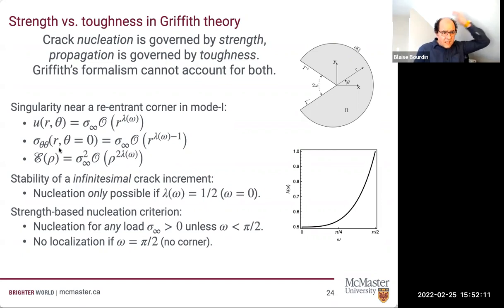If u is in r to the lambda, sigma is in r to the lambda minus 1, then the elastic energy density is the integral of sigma squared. So if you look at the elastic energy in a ball of radius rho centered around the crack tip, it is going to be in rho to the 2 lambda. Then you play the trade-off game: introduce a crack of radius rho, that adds something of order rho to the energy, but may release up to rho to the 2 lambda. And instantly, you see that you can only nucleate a crack if lambda is equal to 1/2.